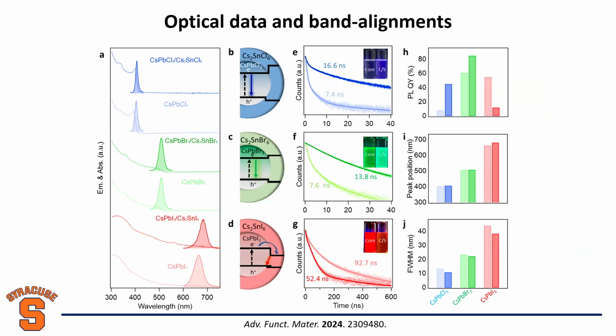For example, for CsPbCl3/Cs4SnCl6 core-shell nanocrystals, they're type 1 core-shell nanocrystals. Here's a band alignment. Basically, the band gap of the shell material is much wider than the core. Both electrons and holes are confined within the core material. So basically, the shell just acts as a protection layer. You're not going to change the charge carrier properties. But in this case, because the shell protects and is more stable, there is much higher emission efficiency, or emission quantum yield. Same situation for bromide core-shell nanocrystals. So you can see in this case, they're very promising for LED application. You want to make very intense light emitters, light devices, right?